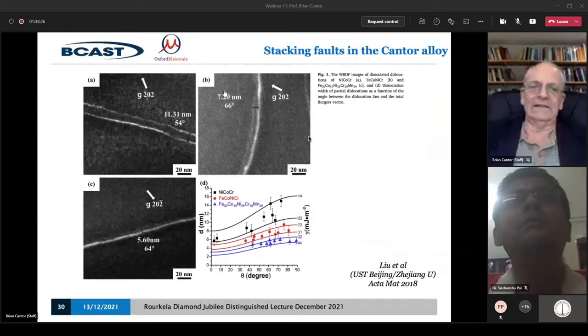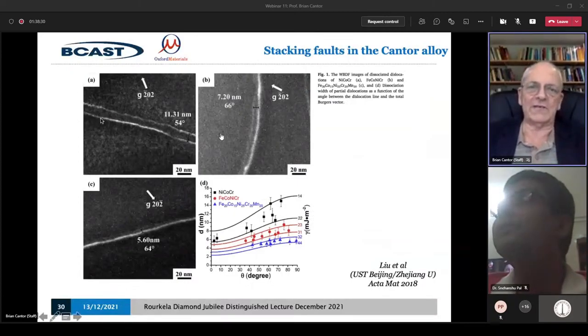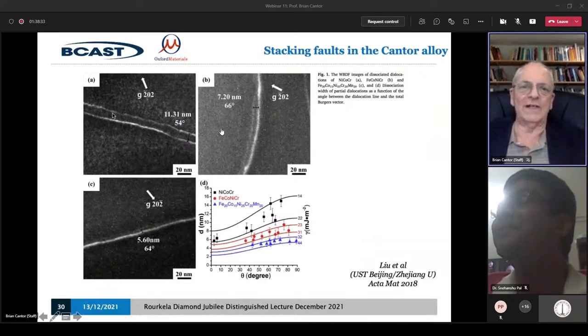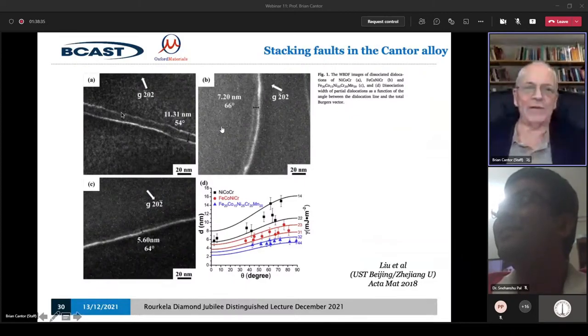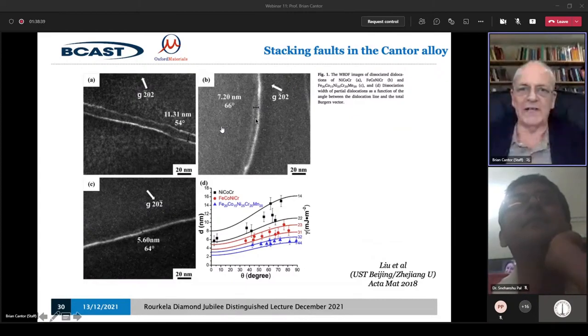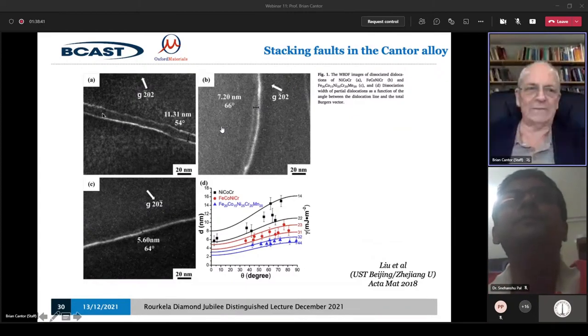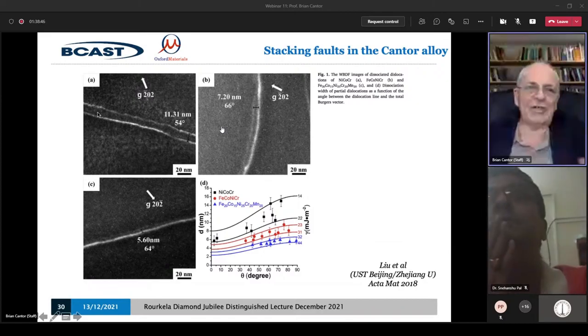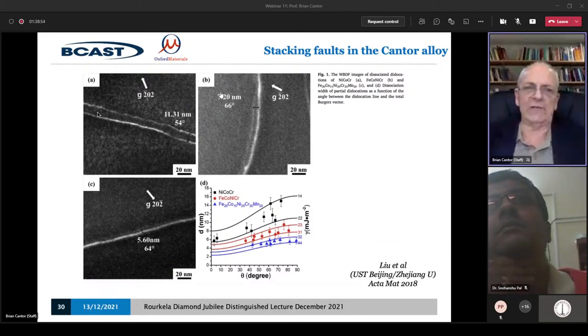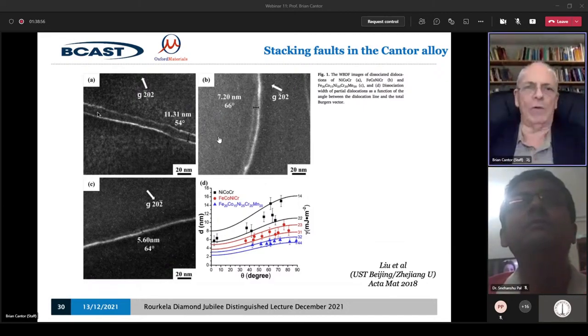These are the dislocations I showed you here, and I didn't talk about this. Sometimes in this talk I do talk about it. These are what are called two partial dislocations. Here's another example of two partial dislocations. And the separation between them is a stacking fault. The conventional dislocation in FCC, the most common dislocation, is a 110 dislocation, which glides on a 111 plane.